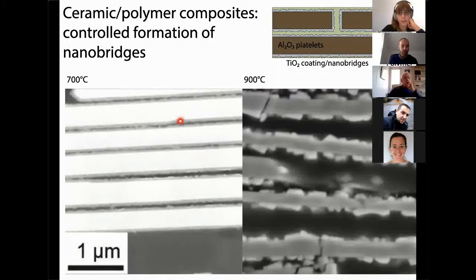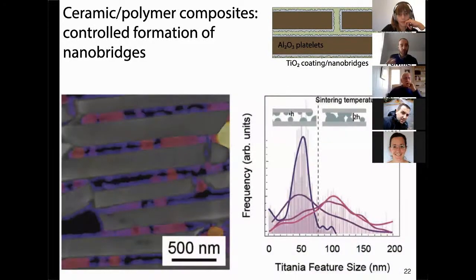The good thing is that because these two solids don't really like each other, when you start heating up, the coating here actually starts de-wetting. Or actually, you have some coarsening of the grain here. And so you can see we can go from, at 700 degrees when you heat it up, very small grains at the interface and some bridges here, to something that is very much coarsened with much bigger mineral bridges. So the first challenge was to be able to quantify the number of mineral bridges in a meaningful way.